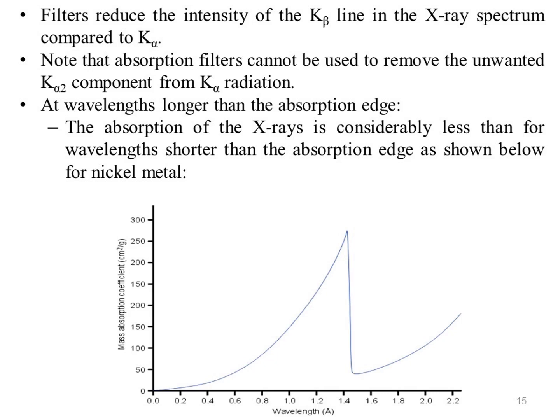Filters exploit the X-ray absorption edge of the particular element. At wavelengths longer than the absorption edge, that is just above the edge, the absorption of the X-ray is considerably less than at wavelengths shorter than the absorption edge, which is just below the edge, as shown below for nickel metal.